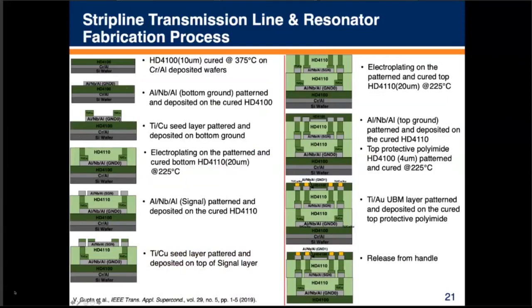So you can see in this case, we're using HD4110. That's a photoimageable polyimide, so we can make nice clean vias. In this case, we're electroplating for the vias between the different layers. Aluminum, niobium, aluminum is used for the signal layer. And we do a thin layer of aluminum before and after the niobium. We're using aluminum, niobium, aluminum because that can help protect the niobium during the subsequent fabrication processes.